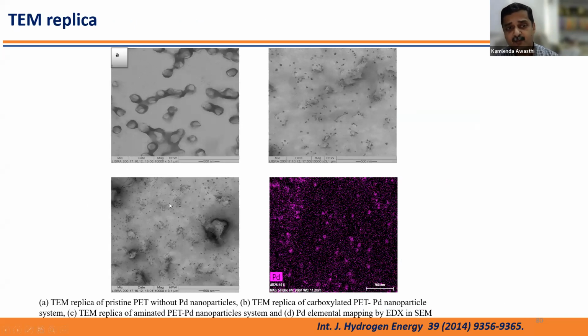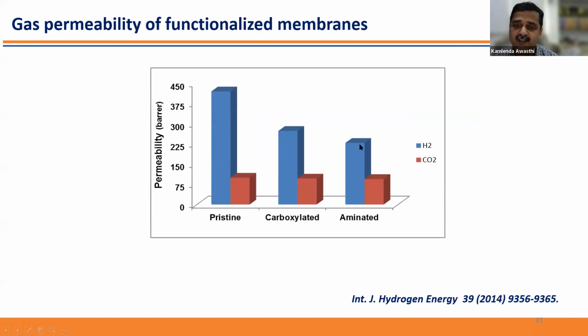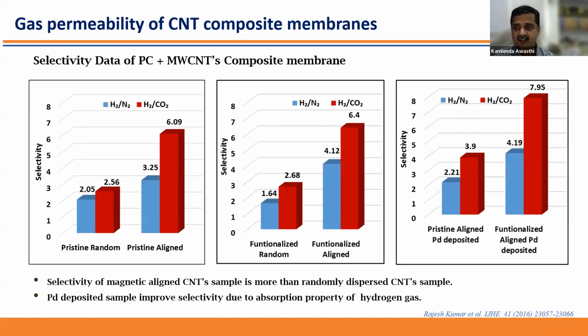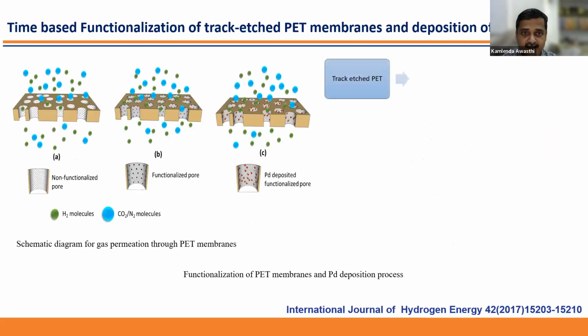So what is happening here? Most of this hydrogen is being absorbed within these palladium nanoparticles. So permeability goes down, but at the same time the selectivity improves, because it is not affecting the permeability of carbon dioxide. So this way we are getting good selectivity of gases in the aminated membrane. We tried a similar approach with carbon nanotubes also. We functionalized these carbon nanotubes, and then we deposited the palladium nanoparticle on the CNTs, and then we aligned them in a polymer matrix. So such membranes are also useful to have better selectivity.